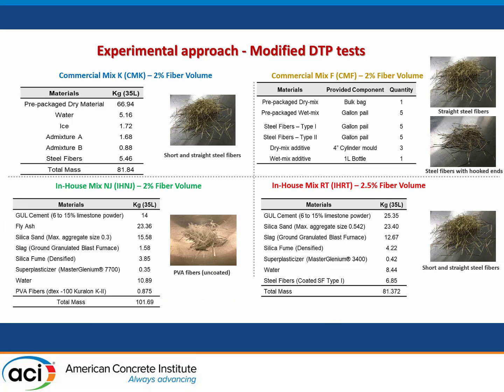So of the four different mixes that we used, one was a commercial mix with 2% fiber volume, uniform straight fibers, 13 millimeter long. The other commercial mix contained a cocktail of fibers, same volumetric ratio, but 50% of the fibers were straight steel fibers, the other were hooked fibers. The in-house mix had PVA fibers, and the other in-house mix also had straight steel fibers, but at 2.5% per volume. All the UHPC materials had a compressive strength around 130 megapascals. The PVA, the ECC material, had a strength of about 60 to 70 megapascals.